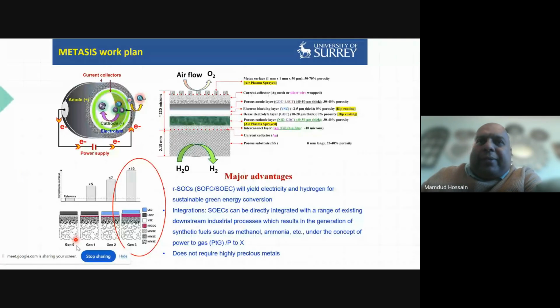Okay, so let's look at the first generation of electrolyzer here. We have a thick cathode, then the electrolyte, then the anode. Looking at the materials used, we mainly use nickel and YSZ on the cathode side. In the middle part, which is the electrolyte, we use YSZ because YSZ is good for ion conductivity. It doesn't allow any other material to flow through except ions, and it is dense, with no porosity. This side has a porous material made of nickel and YSZ.